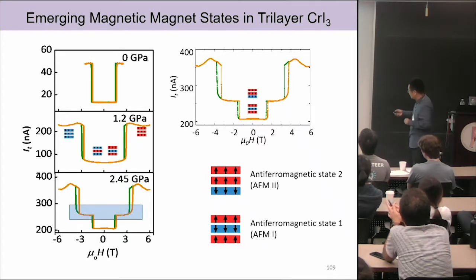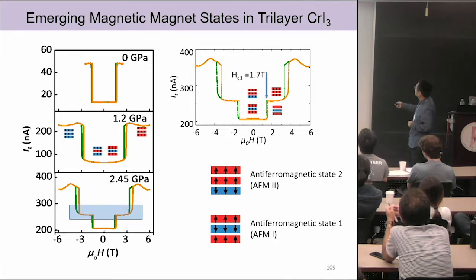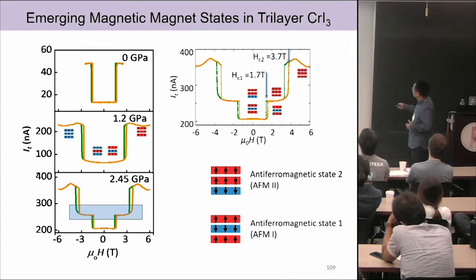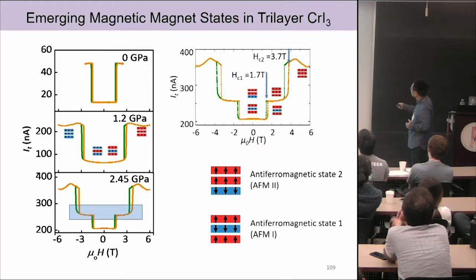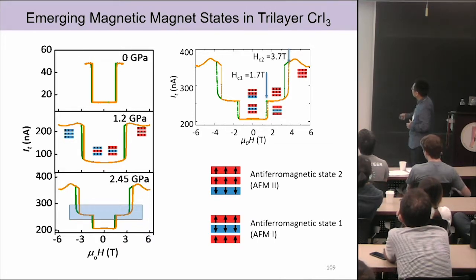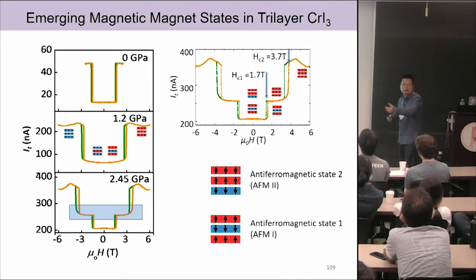Very simple argument. So we can see there are two spin flip transitions. The first transition happened at 1.7 Tesla. The second is, roughly speaking, about twice that, 3.7 Tesla. So the first spin flip transition is actually pointing to AF2 flipping into the ferromagnetic state, and the second transition corresponds to the AF1 spin flip transition into the fully spin polarized state.